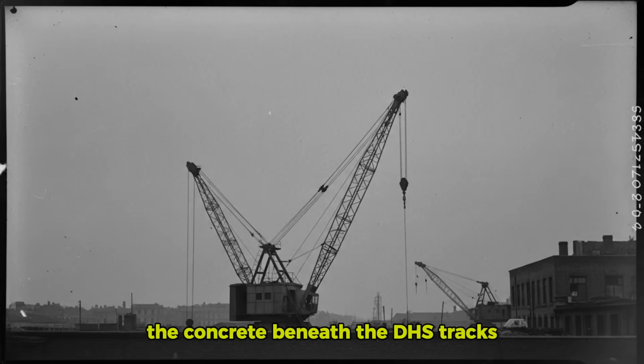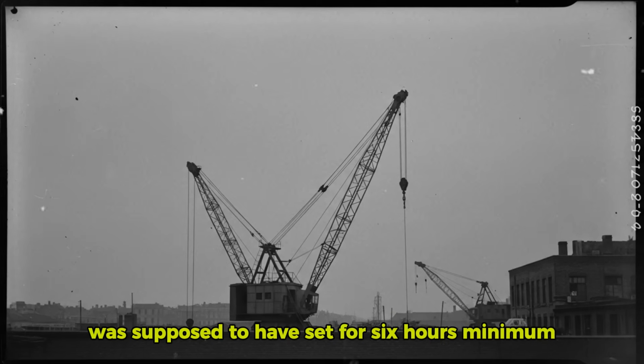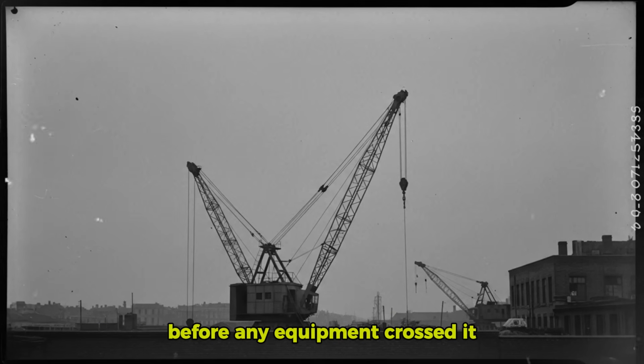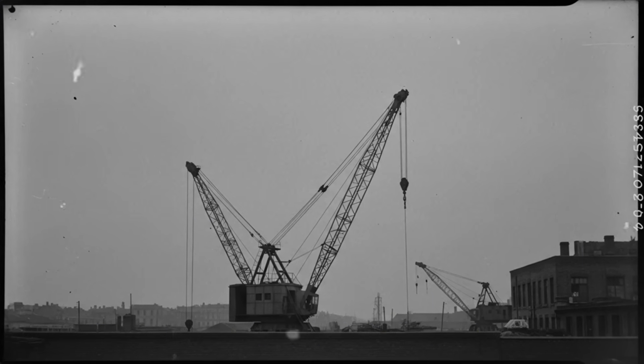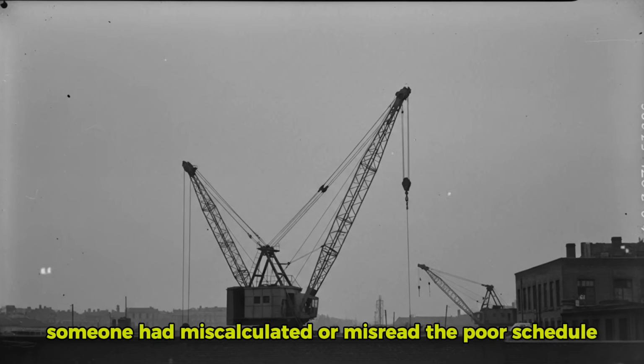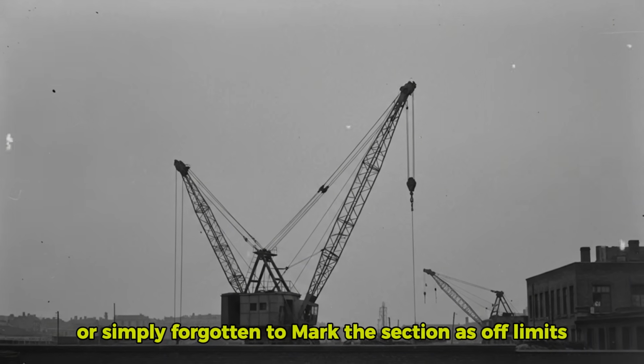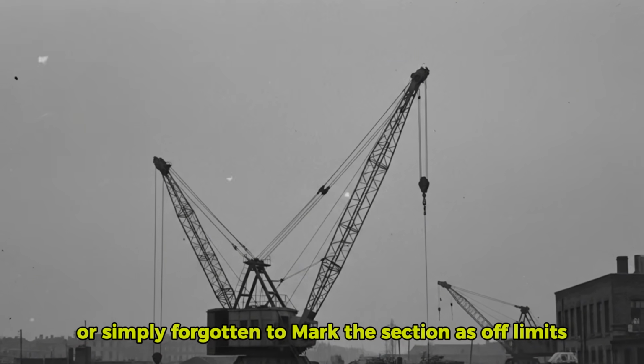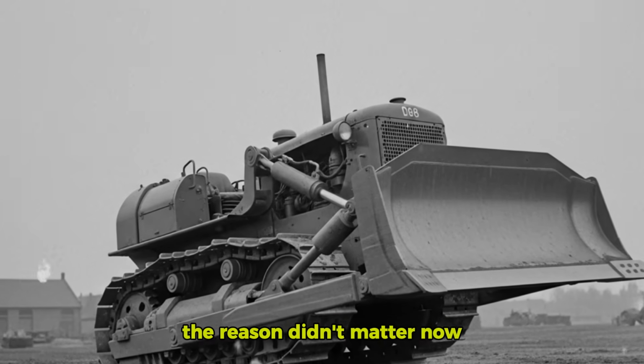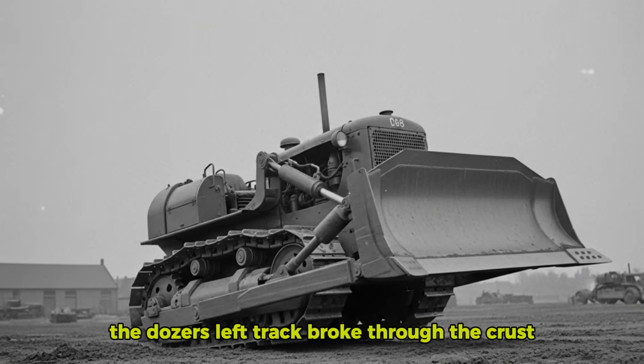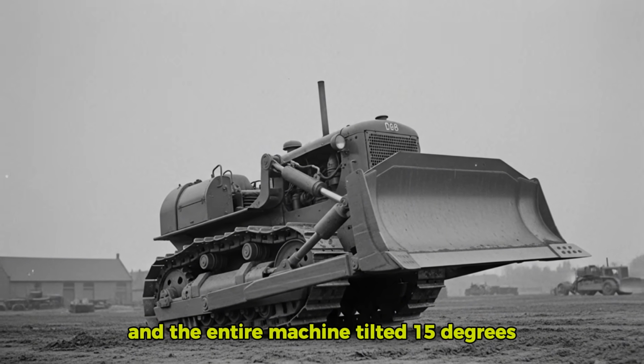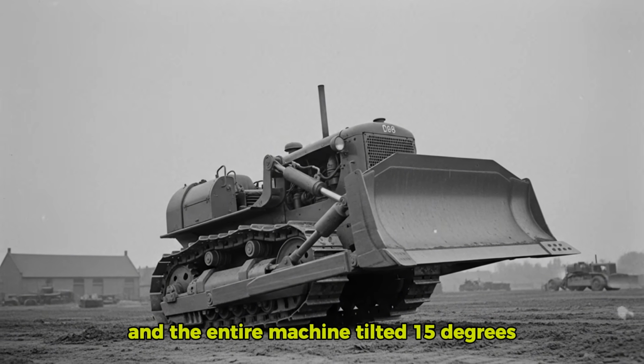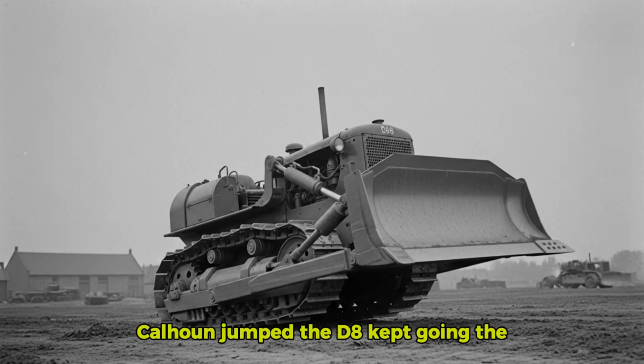The concrete beneath the D8's tracks was supposed to have set for 6 hours minimum before any equipment crossed it. Someone had miscalculated or misread the pour schedule, or simply forgotten to mark the section as off-limits. The reason didn't matter now. The dozer's left track broke through the crust and the entire machine tilted 15 degrees. Calhoun jumped. The D8 kept going.